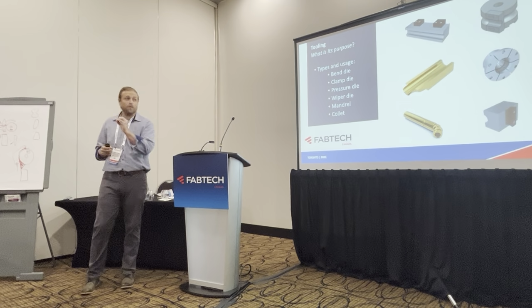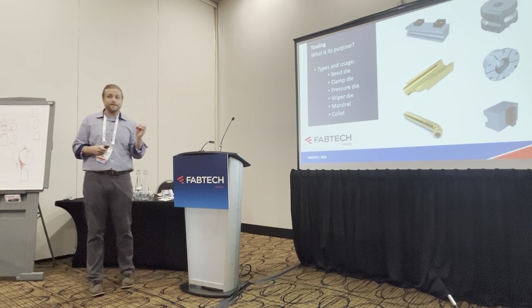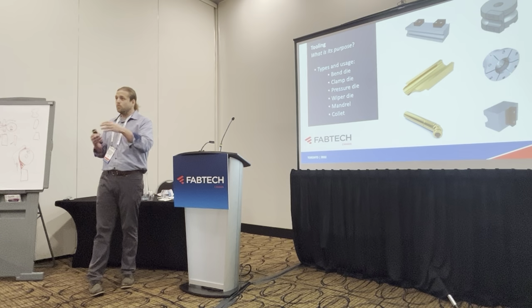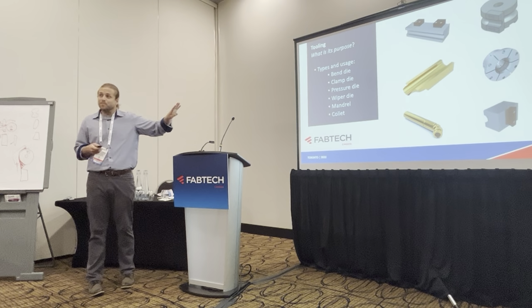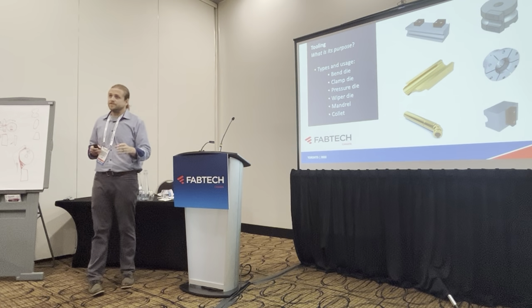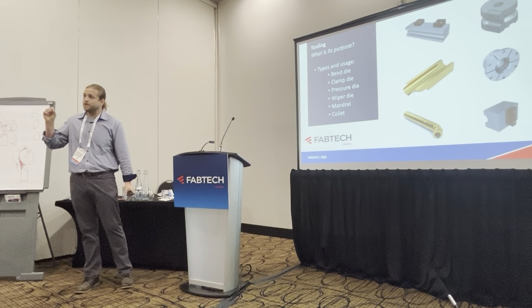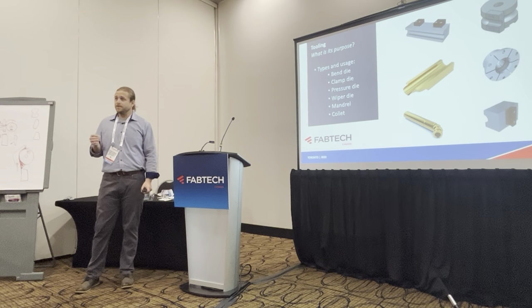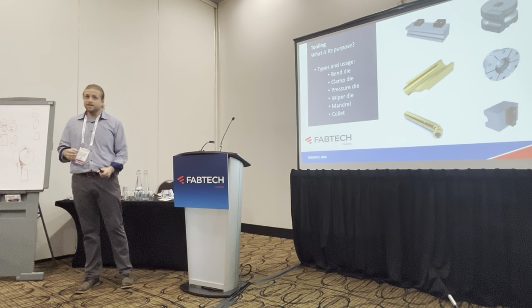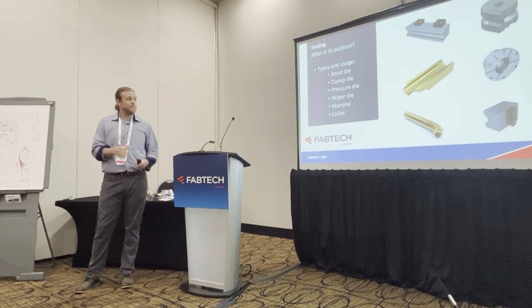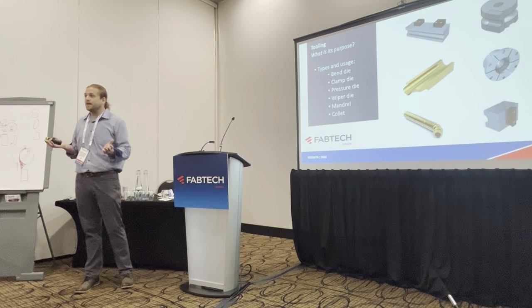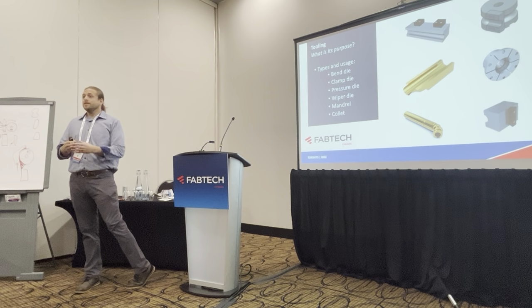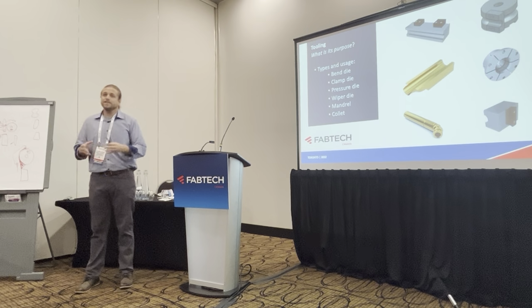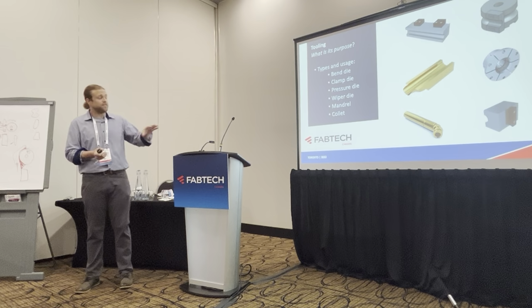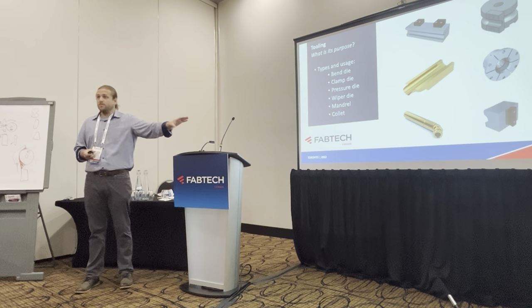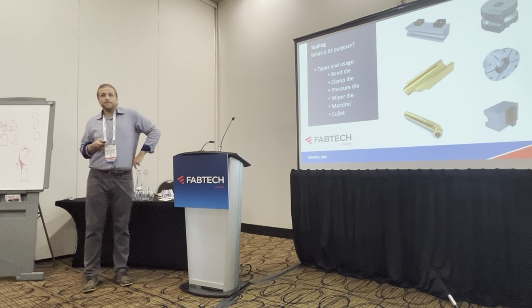Wall thicknesses play a huge role in your mandrel. Aluminum specifically, if you say you have a 1-inch OD, .120 wall aluminum, you're going to most likely need three mandrels all sized a little bit differently due to an ASTM standard of that wall fluctuation in aluminum. Aluminum, you see that the most. You do see it with steels and stainlesses. As you get to that tighter bend, you want to close that gap up on the ID of the tube. And as you get closer to, say, maybe 3/1000ths on both sides of the mandrel to bend, now if the wall thickness fluctuates, say 10, now you have a chance of that mandrel not fitting. So sometimes you have to have multiple mandrels just to bend one job. Did that help answer your question? Okay.